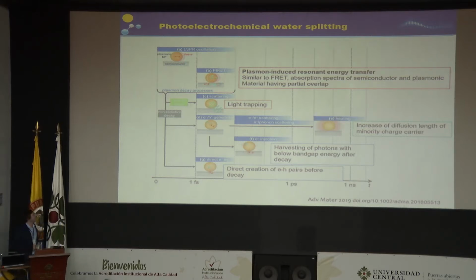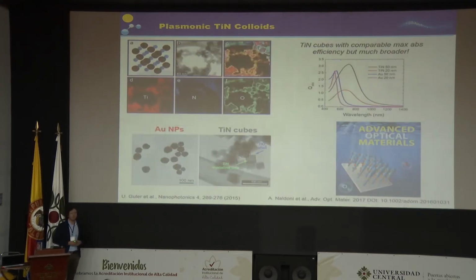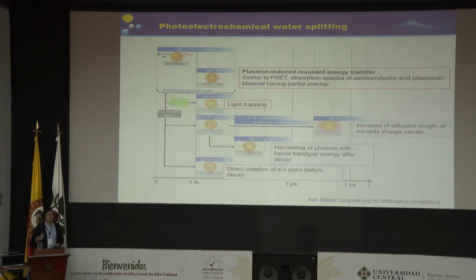So let's say that we use titanium oxide, which has a band gap of 3.2 eV, or which absorbs up to 420 nanometers. So we can also use energy which comes from the spectral region of 500, 700, and 800 nanometers. So we can use different plasmonic materials, excite the plasmon, and use the hot electron which decays from them. And so this means that we have a photoresponsivity from the device which comes not only from the region of the band gap, but also from using below band gap photons. So of course this can be an interesting way to enhance the activity of our materials.